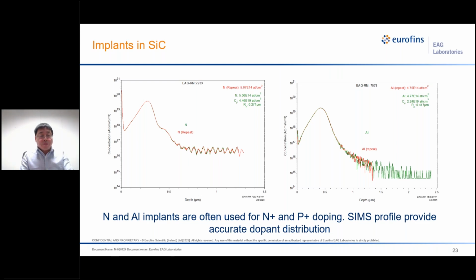I want to add a few more comments here, because for the N-type and the P-type ohmic contact in the device, usually they need a constant level of doping at least E19 to E20 level. So in that case, multiple implants are required. And one feature for silicon carbide is when you implant the species, it will not diffuse. This is different from silicon.